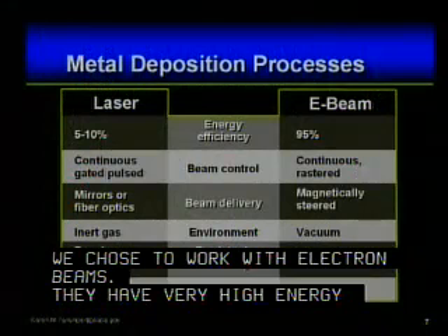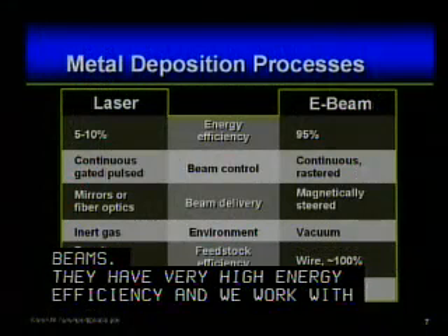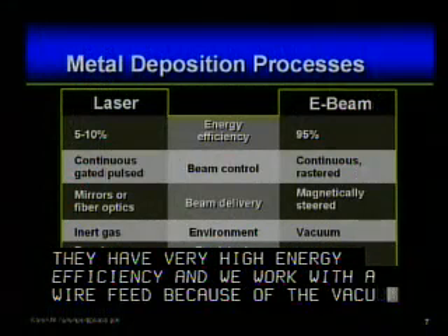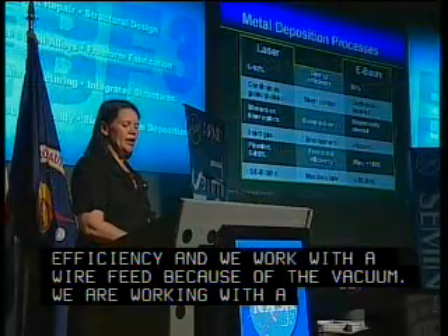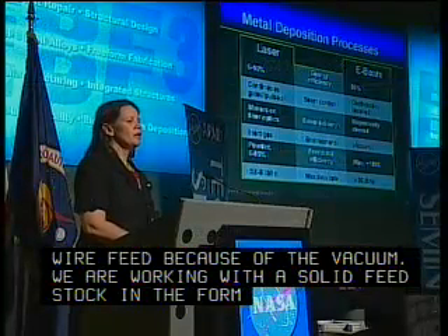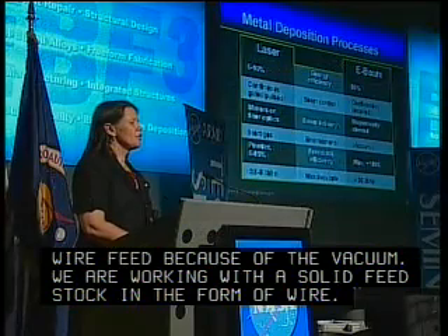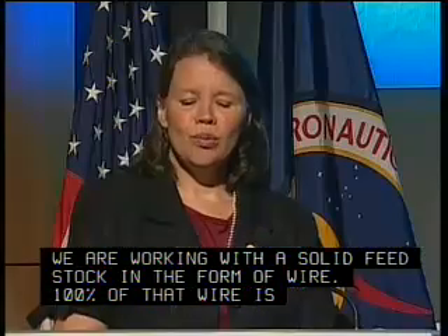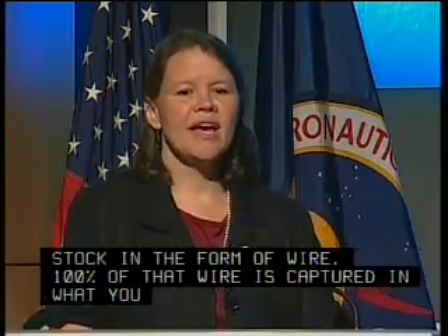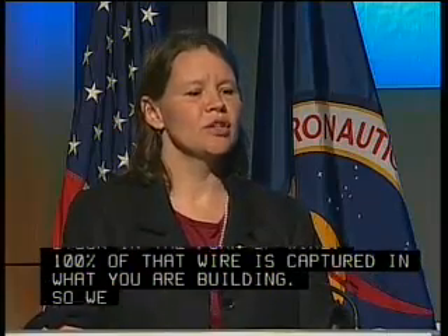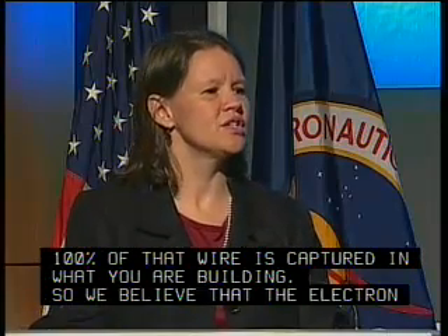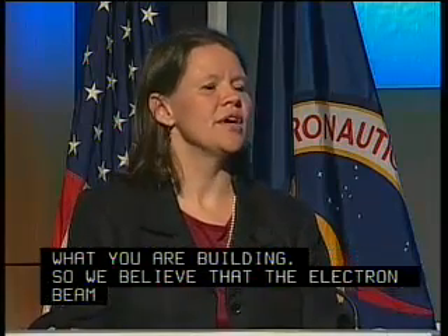We're working with a solid feedstock in the form of wire, but 100% of that wire is captured into the part that you're building. And we've demonstrated deposition rates on the order of 30 pounds per hour. So we believe that the electron beam process has commercialization potential, and it solved many of the problems that existed with the state-of-the-art in 2001.